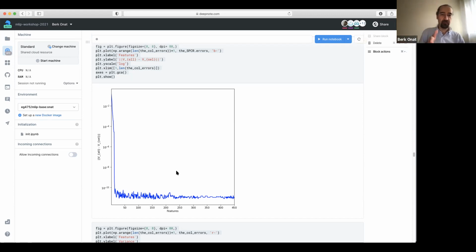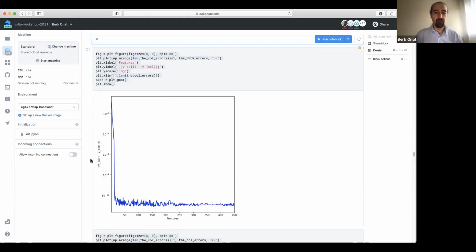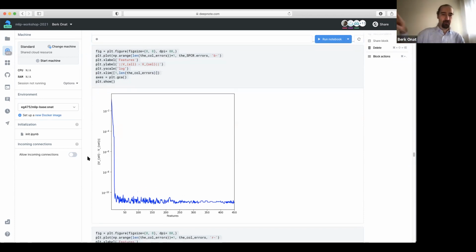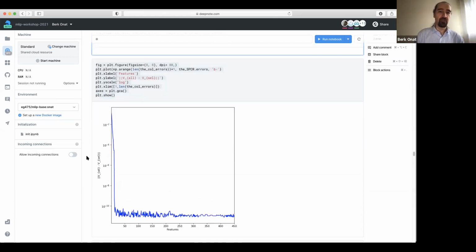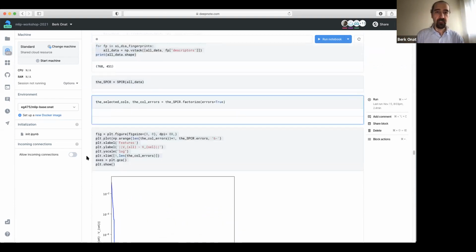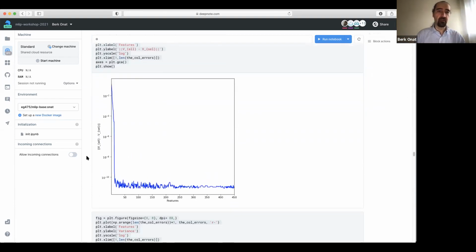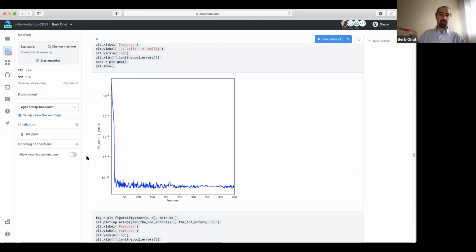Now it goes flat immediately after 2%, because the structures that we are putting in are just crystal structures. And there's one amorphous structure, but probably it's also because in the amorphous distribution of this silicon, the closer atoms have this second peak, but the rest turns out to be far away. So if you know the radial distribution function, maybe we are not expanding that much and don't need that many features. So when you do that, you can see a lot of this information is actually flat.